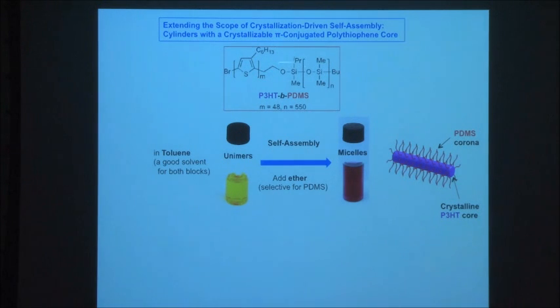When you have the unimers, so when this is dissolved in solution, the poly-3-hexylthiophene repeat units, the thiophene rings, are out of plane in solution because they're dissolved. And so the extent of pi conjugation is very low. So you have a yellow solution. But then as you add a solvent that's selective for PDMS, such as ether or heptane or hexane, this will assemble. The poly-3-hexylthiophene will precipitate and crystallize, and you get micelles. As they crystallize, you enforce coplanarity of the thiophene units, and this gives you extended pi conjugation, and so you see a red shift in the color, and it goes purple.